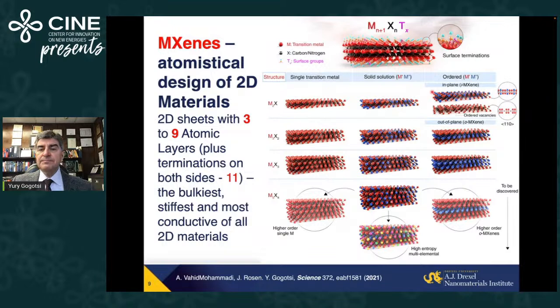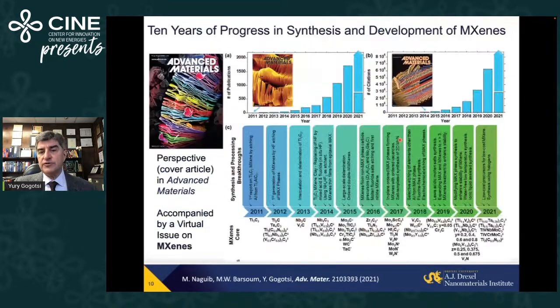But we can also make in-plane ordered materials with alternating atomic columns of different elements. Maybe better to see in the cross-section. And those elements, if they are rare earth metals, for example, or yttrium, scandium, can be etched away, leaving lines of divacancies. And we can build also solid solutions on the X side, carbonitrides, but also on the M side, as shown here, like metal alloys. And if you take 3 to 5 transition metals, you can get high entropy multi-elemental MXenes. And of course, don't forget about surface termination. So pretty much what we show nowadays, we push nanotechnology to a level where we can truly design 2D materials with a huge variety of properties.